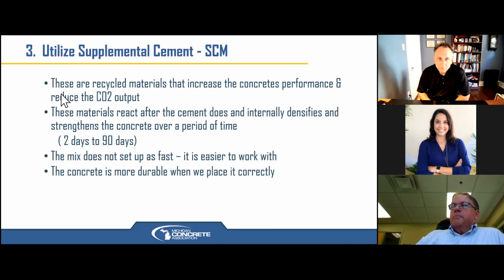So the other big step to take is the utilization of supplemental cements. It's fly ash, which is becoming harder to find, but the slag cement supply in Michigan right now is pretty sound, and we're relying on that. One of the things you will find when you use supplemental cements is that you will gain significant strength between age 28 and 90 days. With some of the type 1 cements, once you got to 28 days, there wasn't much bump between 28 and 90. But what this tells you is that the reaction with the supplemental cements is ongoing for a much longer period of time. The mix doesn't set up quite as fast. It's easier to work with. But we get some really good long-term durability if we allow it to fully gain this internal strength that really locks it together.